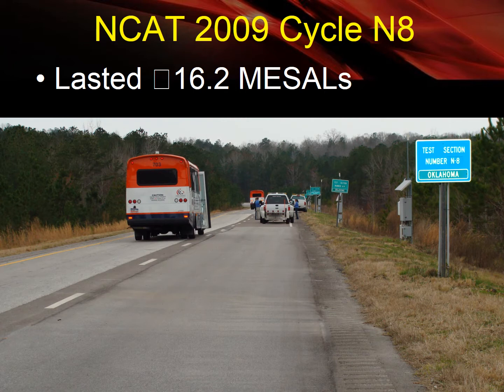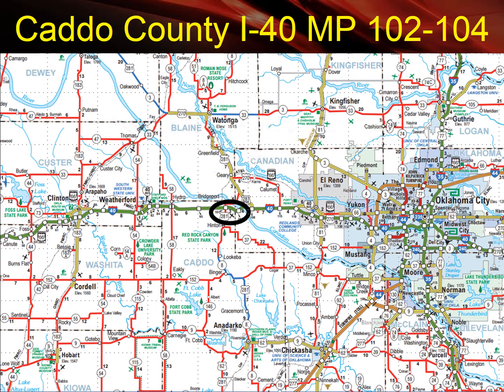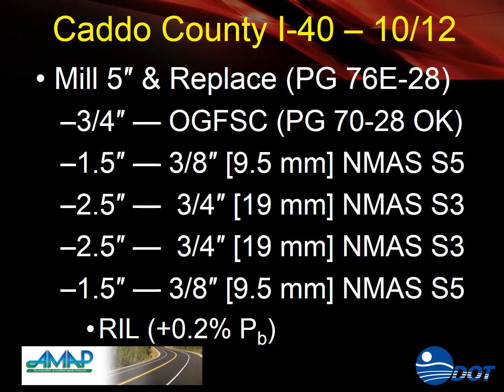So at the end of the 2009 cycle, we went out on a sponsor tour, and this is what it looked like. And that's not too bad. Well, the Caddo County project, like I told you, was I-40 milepost 102 to 104. There's Oklahoma City, and the project is between Watonga and Hinton exits. And we did a similar thing that we did on the NCAT test track, only we used an OGFC for the wearing course, and they like it out there. It's a good safety layer.